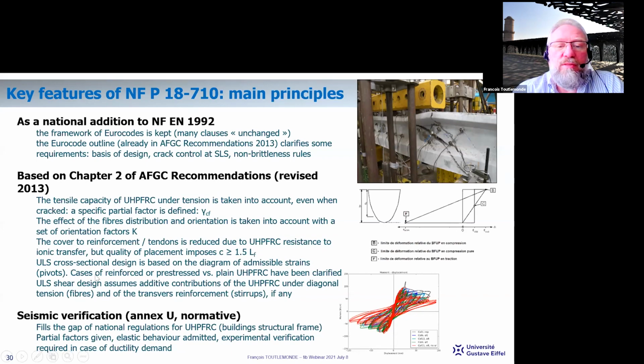The ULS cross-sectional design is based on a diagram of admissible strain, in continuity with reinforced and pre-stressed concrete. But the cases of reinforced or pre-stressed concrete versus plain UHPFRC have been clarified with specific ultimate strain requirements in this diagram. The shear design assumes an additive contribution of UHPFRC under diagonal tension, brought by the fibers, and the transverse reinforcement — the stirrups, if any. We also had to fill a gap with seismic verification, because seismic resistance is a legal issue in France, so partial factors are given. The elastic behavior of the UHPFRC frame structure is admitted, and an experimental verification is required in case of a larger ductility demand.